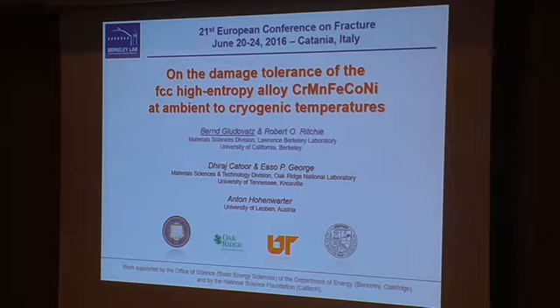When we zoom into the fracture surface, this was the same for all three different temperatures. We get fully ductile fracture with a lot of voids, but also a lot of particles all over the fracture surface. We have tried to do some statistical analysis on these particles, and found an average particle size of about 1.6 microns and an average spacing of about 50 microns, even though these numbers should probably be taken with a grain of salt, as it's not that simple to really do good statistical analysis of so many particles.